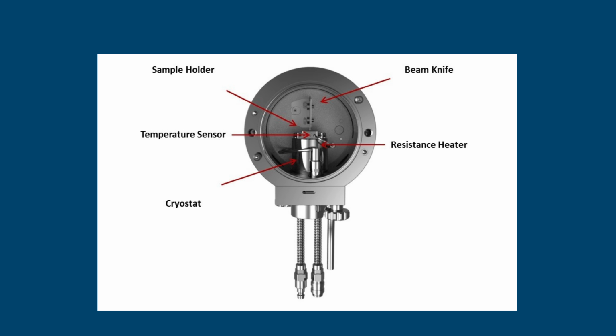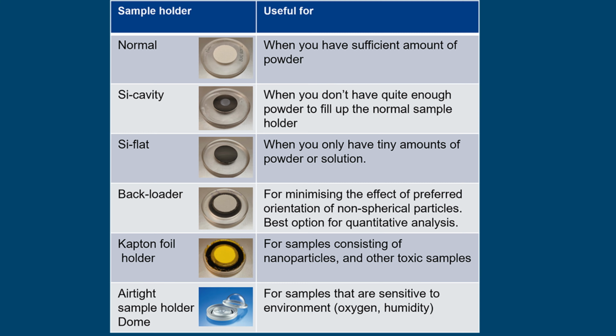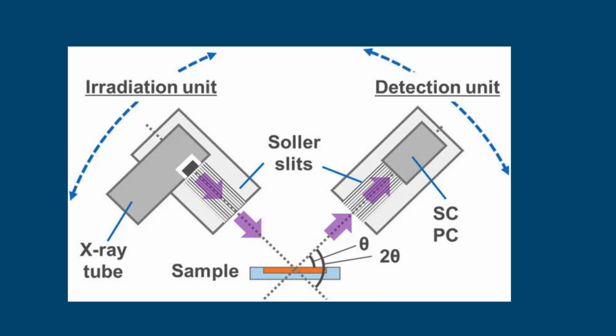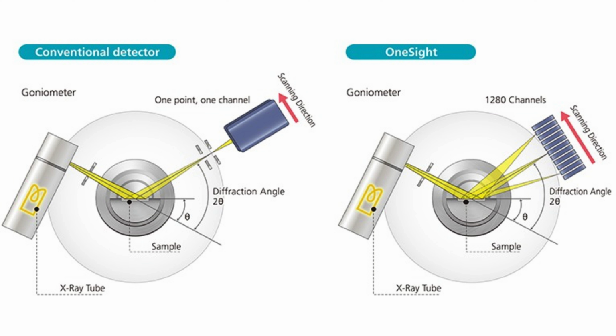The sample holder positions the specimen within the X-ray beam path. Precise alignment is essential because even minor displacement can alter diffraction angles and introduce systematic errors. Sample holders are designed to minimize background scattering and maintain stable orientation during rotation. The detector records the intensity of diffracted X-rays and converts the signals into electronic data. Modern detectors provide rapid acquisition, high sensitivity, and improved signal-to-noise ratios compared with older scintillation counters. The collected diffraction data are processed computationally to generate diffraction patterns for structural interpretation.